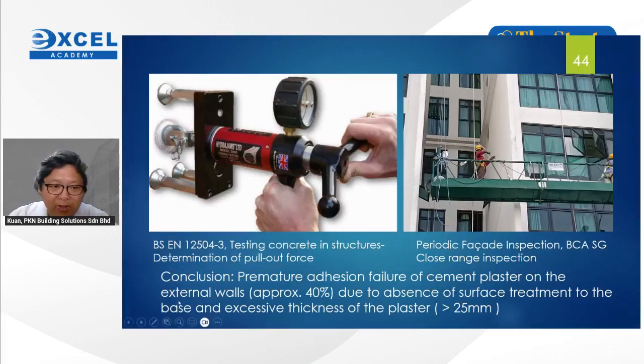Of the cement plaster on the external wall, the delaminated area and the area with risk of delamination is more than 40%. The reason is the absence of surface treatment on the base and the excessive thickness, more than 25 mm. In some areas which are thin, even though it cracked, it didn't delaminate. But areas with thick cement plaster above 25 mm, even without cracks, delaminated. So we can come to a conclusion that the delamination was caused by negligence.